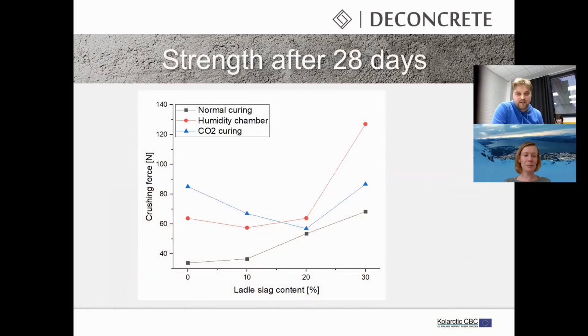And here is the strength of the granules after 28 days of curing, as a function of the ladle slag content. As we can see, when the ladle slag content is low, like 0 to 10, carbonation curing is the most effective way. When the ladle slag content increases, then humidity and normal curing are also quite suitable ways. I found the biggest strength with the humidity chamber with 30% ladle slag. So I think that a high amount of ladle slag produces a hydration reaction, so it makes the granules strong.